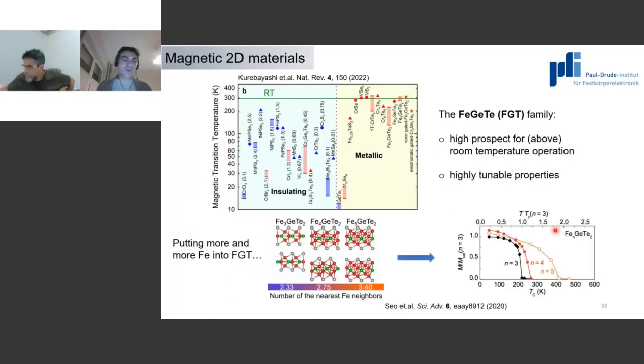And now you already have, in 2022, a review showing experimentally validated results for all different kinds of 2D magnets. I just want to call your attention to this metallic system, iron germanium telluride, which I call the FGT family, because if you look here, they have a very high transition temperature, always around 300 Kelvin, and they also have highly tunable properties. For instance, if you change the iron concentration, in principle you can still keep the van der Waals structure, meaning a layered material that would allow you to go to a pure monolayer, and have a very high TC that will actually increase with the amount of iron because you increase the number of nearest iron neighbors.